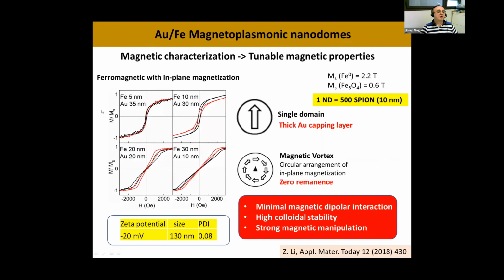We measure the magnetic properties by changing the ratio of iron to gold. For example, here we have 5 nanometers of iron and 35 nanometers of gold. The total thickness is always 40 nanometers. When we have 5 or 10 nanometers of iron, we see a single domain behavior, meaning that all the moments point in the same direction, like this. However, as we increase the thickness of the iron layer, the system no longer has a single domain behavior, but has what is called a magnetic vortex behavior, where the magnetization curls around the spherical shape of the nanodome.